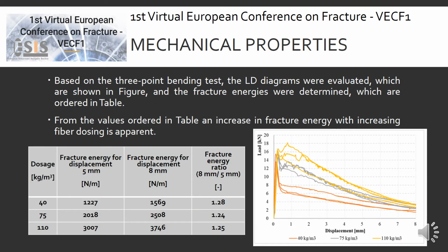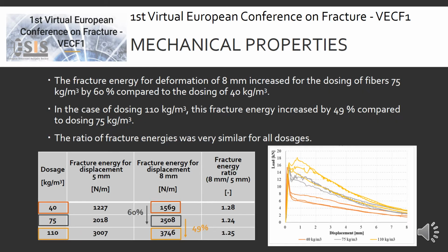Based on the 3-point bending test, the load-displacement diagrams were evaluated, showing the fracture energy for a deformation of 8 mm. For the fiber dosage of 75 kg per cubic meter, it was 60% higher compared to the dosage of 40 kg per cubic meter. In the case of dosage 110 kg per cubic meter, the fracture energy increased by 49% compared to dosage 75 kg per cubic meter. The ratio of fracture energies was very similar for all dosages.